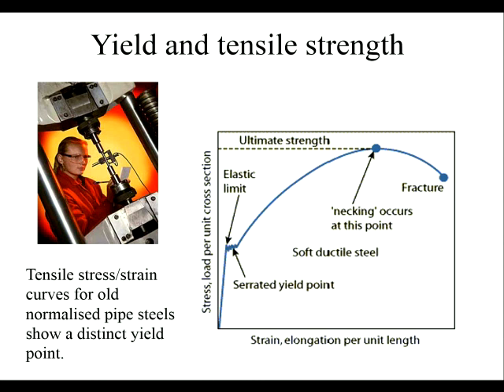So you get an elastic part, and then you get some sudden wobbles, a serrated yield point they call it here. And then you get work hardening, and the stress will go up to an ultimate strength. And at that ultimate strength, you get what's called a plastic instability. So the material, instead of being a cylinder, starts to neck down locally and become thinner. And then the stress drops, but actually the real stress goes up. The engineering stress, based on the original area, drops, but the real stress, based upon the actual area, goes up. And then finally you get fracture.